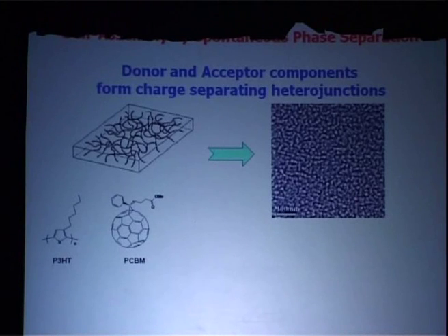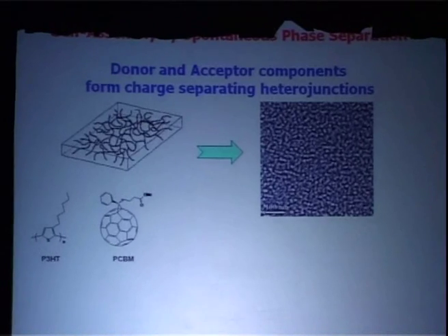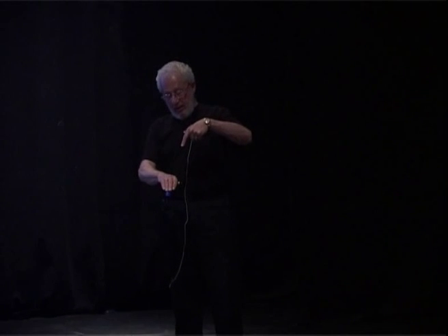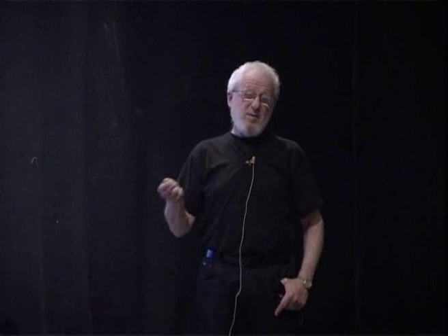The contrast comes from the fact that an electron beam going through this material interacts with the carbon nuclei, it's mostly carbon, in the material. The probability of direct Rutherford scattering, for example, direct head-on collision, is very small. So mostly the electrons in the electron beam are small angle scattering. In effect, like an index of refraction in an optical phenomenon. So the electron beam goes a little bit more slowly through the fullerene because there's a higher density of carbon nuclei, a little bit faster through the polymer because it has a little bit lower density of carbon nuclei, and I get the contrast in that way. I'll come back to that.